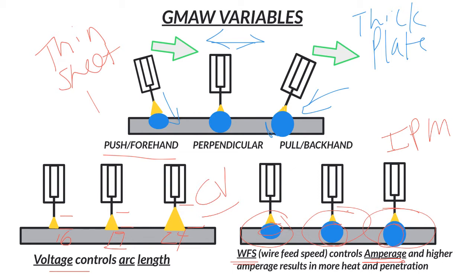So if we get a little bit closer to the metal with our gun, the voltage will drop just a little bit, but you'd be surprised when you look at a constant voltage graph, the kind they have in the textbooks, the voltage will only change a little bit, because it's really changing by the tenths of a volt. And maybe it'll be a full volt, and that's actually quite a bit in welding. You go from 18 to 19, there are some differences occurring, but your amperage will actually spike or drop if you get closer and farther away. A little bit closer would spike your amperage, a little bit farther would raise your voltage and drop your amperage, okay?